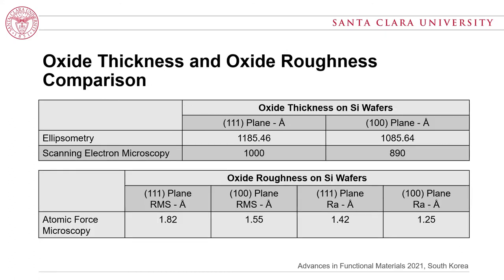Now let's compare results from SEM, ellipsometry, and AFM. SEM and ellipsometry both suggest a difference of approximately 100 Å between the 111 plane and 100 plane, with ellipsometry results representing the average value of four locations per plane. From AFM, due to the slightly higher packing density of the 111 plane compared to the 100 plane, surface roughness results show that the 111 plane has slightly higher roughness. The RMS is the root mean square value of roughness, and Ra is the average value of surface roughness.